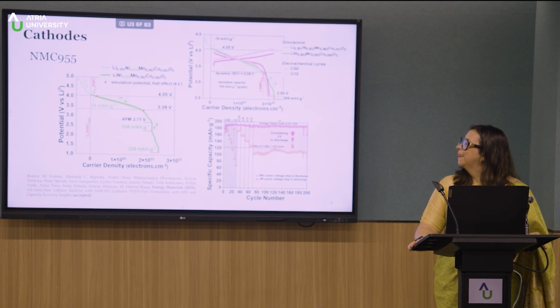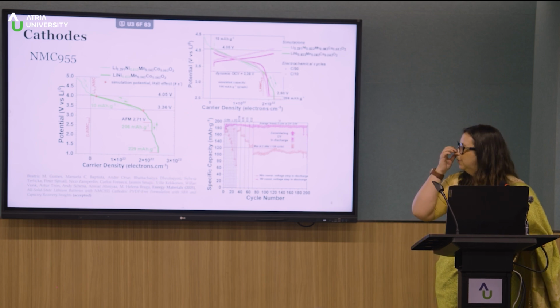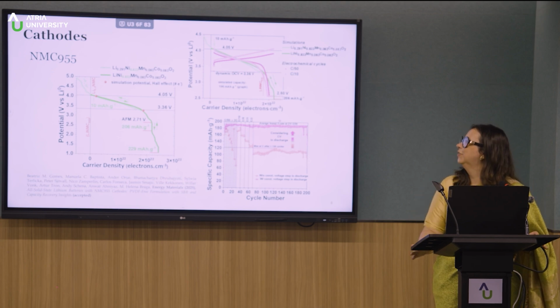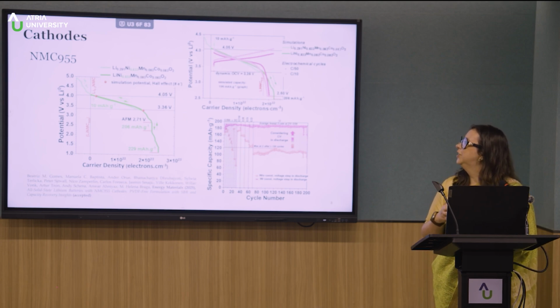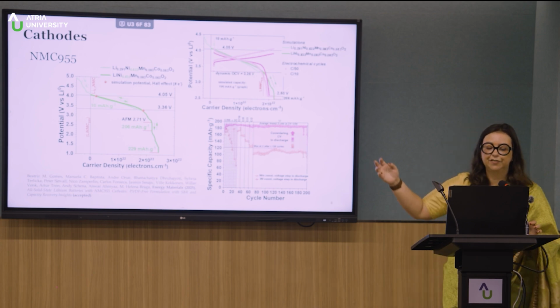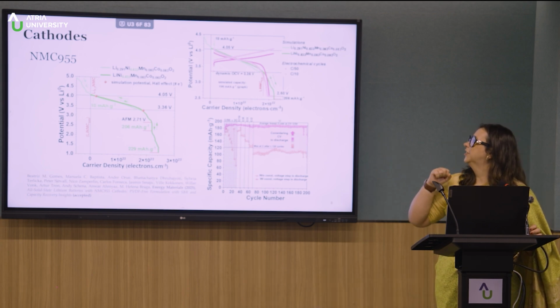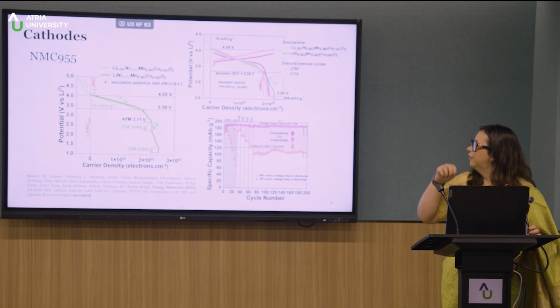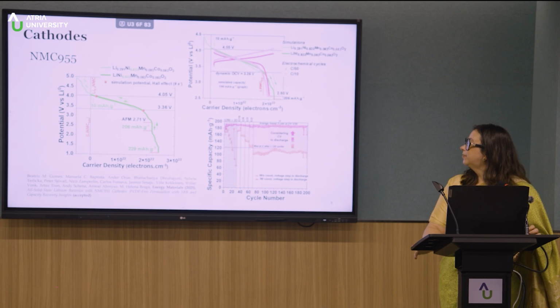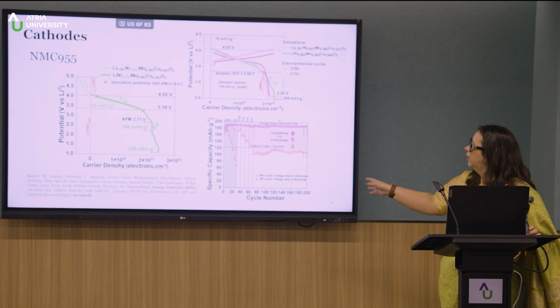So the cobalt needs to be reduced, but it's not that simple to reduce the amount of cobalt, because cobalt helps the structure of the NMC to keep coherence, because of all the magnetic properties of the NMC. So we need to have some cobalt, and this is 5% of cobalt, 90% of nickel, and 5% of manganese. So what did we do in this project? We were able to have many cycles with solid-state electrolytes. You see 200 cycles.